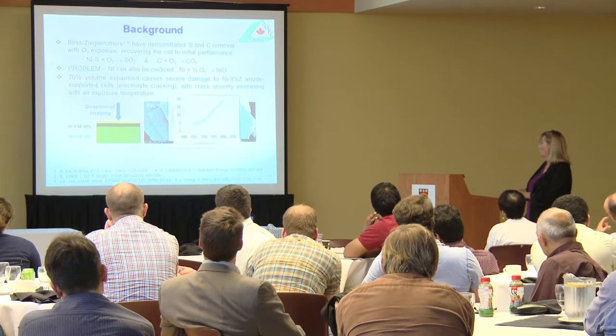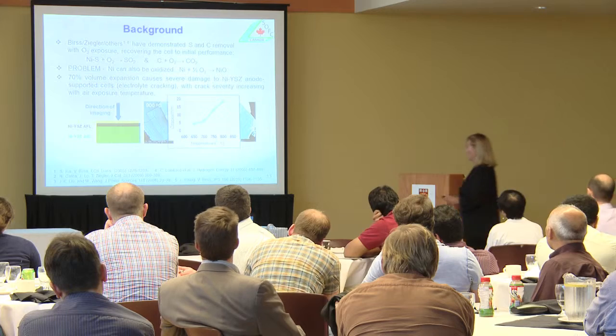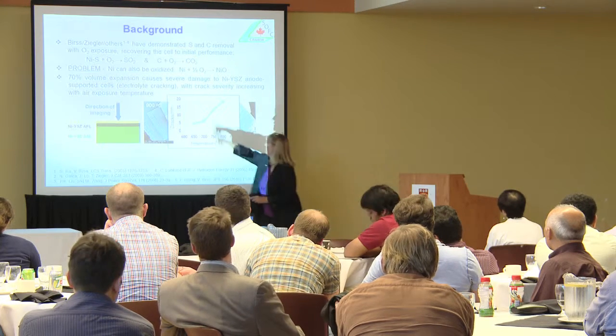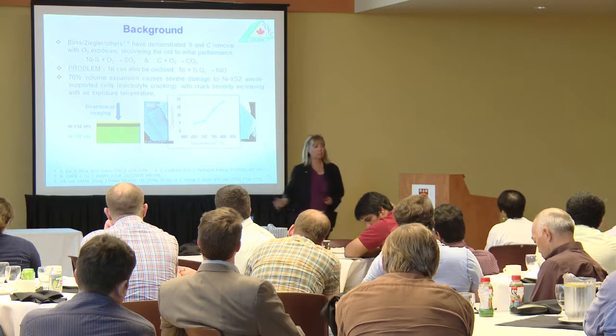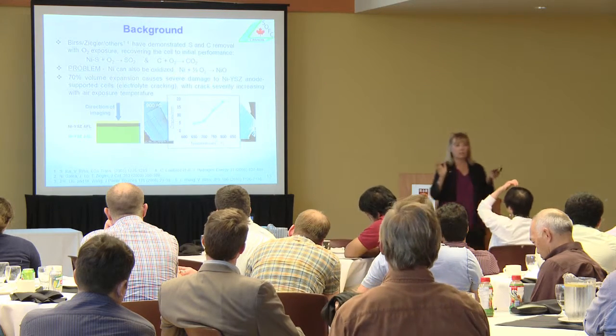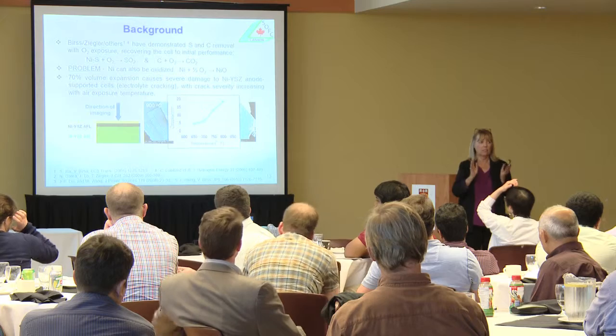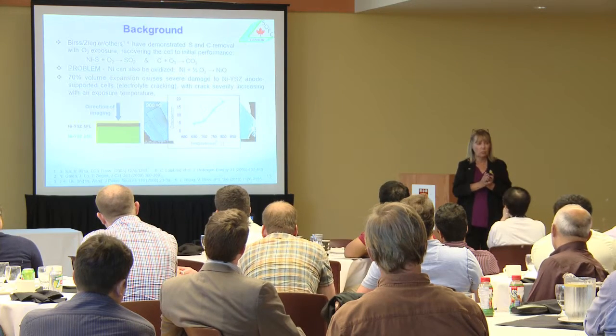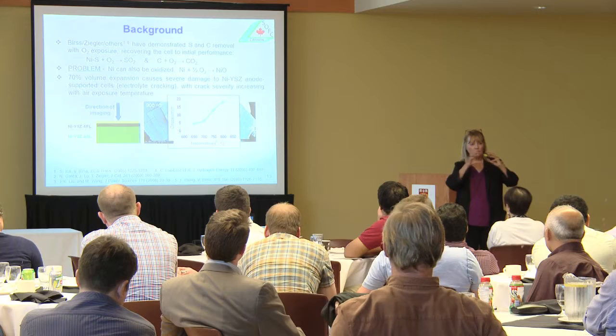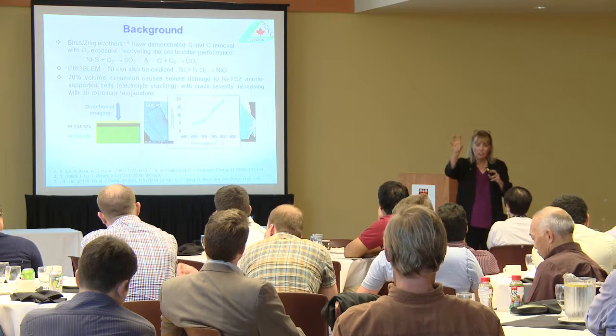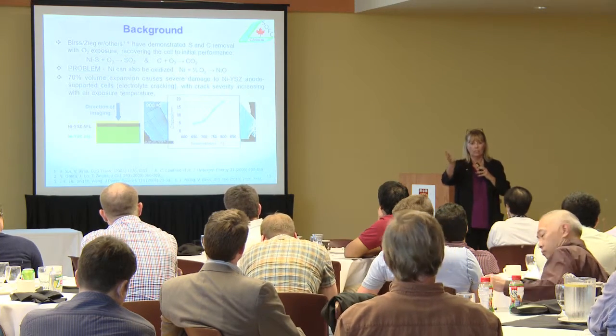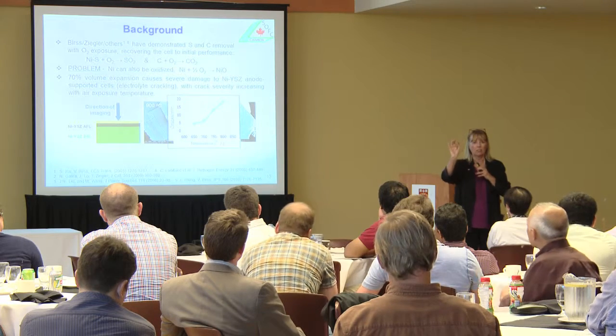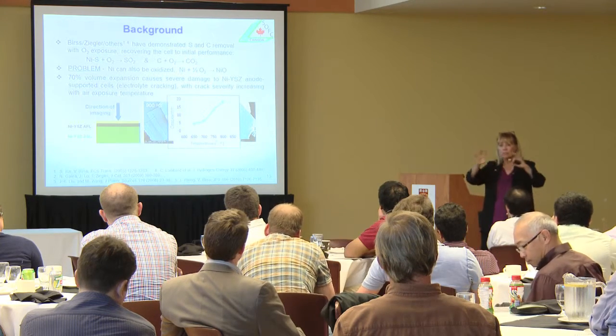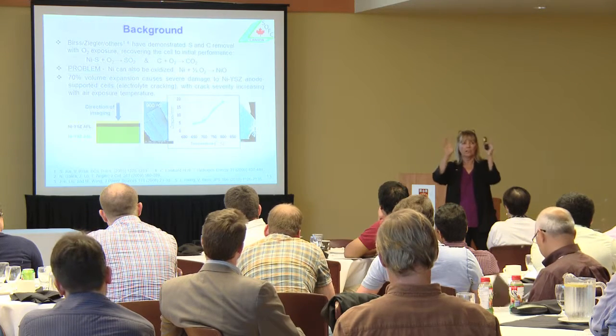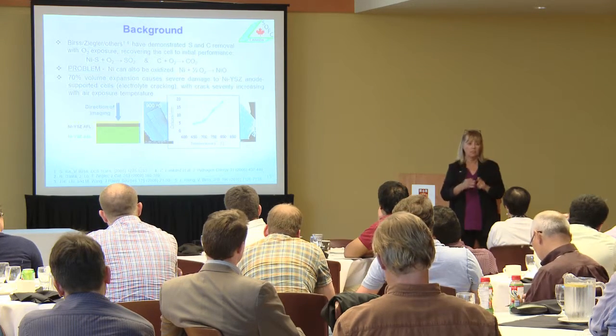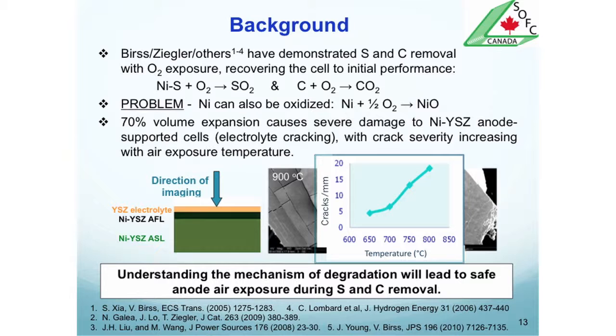We thought this was thermal shock, but it really isn't. The fact that the number of cracks per unit distance versus temperature is much worse there turns out to be about the mechanism of nickel oxide formation. It's such that if you do this at high temperatures, as you start oxidizing it, the outside gets oxidized heavily, the inside is hardly oxidized, and you get this bad gradient that causes increasing stress on the electrolyte, whereas at low temperatures, every nickel particle kind of equally oxidizes, and that's a safer kind of condition. So anyways, we've learned about nickel oxidation.